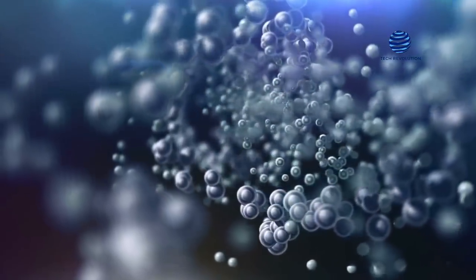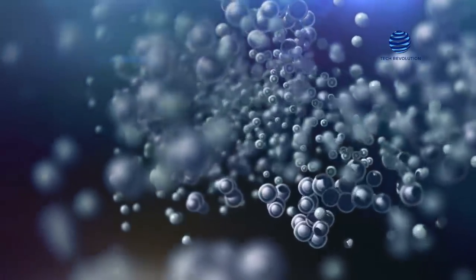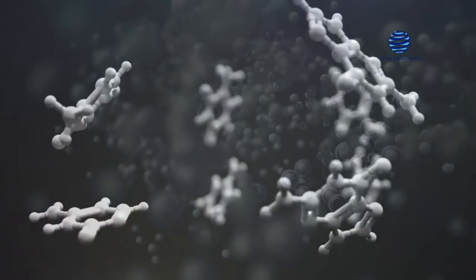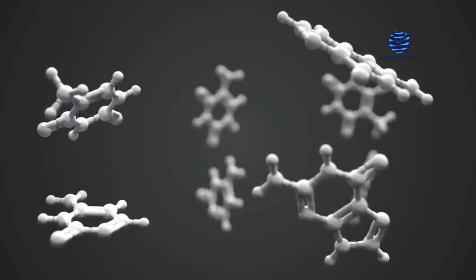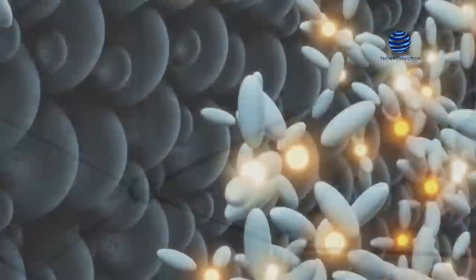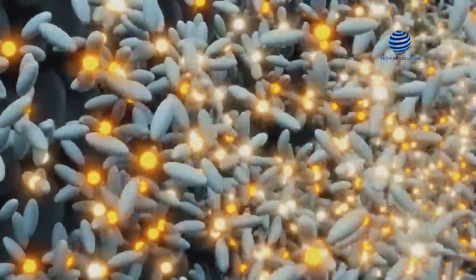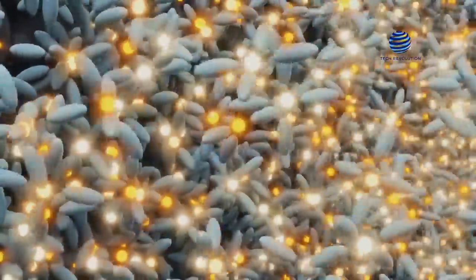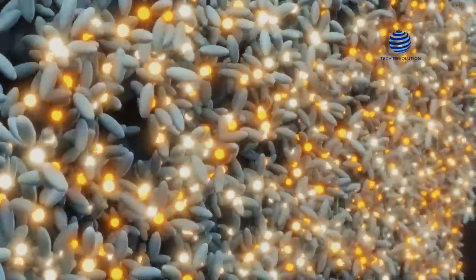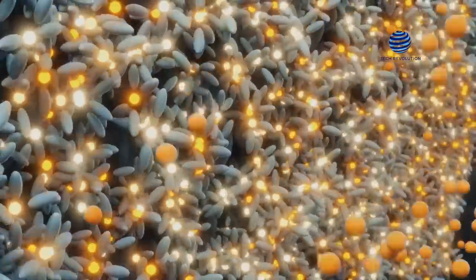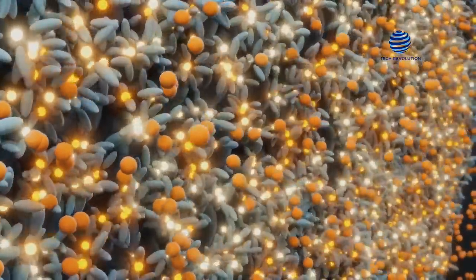When elemental boron is put onto the silver surface in a very high vacuum, a molecular beam epitaxial growth occurs, creating the material. In the earliest published reports, metallic 2D sheets with a distinctive buckled or crinkled surface are stated to have been made and weakly adhered to a silver substrate.